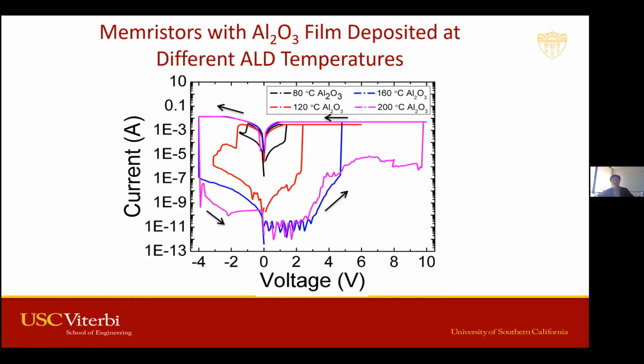You can see that even though the devices have exactly the same stack thickness, they behave very differently. This is the device with aluminum oxide deposited at 80 degrees C, this is 120, this is 160, and this is 200 degrees C. So you can see that just the crystallinity change has a big effect.